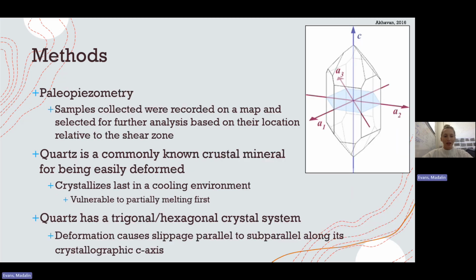For paleopiezometry, samples collected were recorded on a map and selected for further analysis based on their location relative to the shear zone. Recognizing the recrystallization mechanisms that I had just gone over helped partition between the recrystallized grains and the subgrains and relict grains. Petrographic images were processed through an application called ImageJ, in which the recrystallized grain size diameter was obtained by manually measuring each individual grain. Cross-polarized images aided in the final measurement that was obtained by enhancing the grain boundaries.